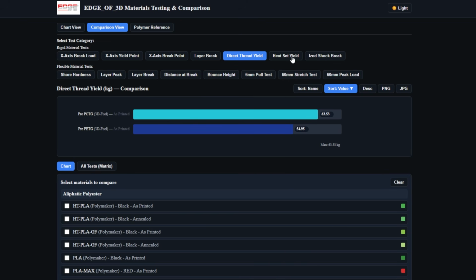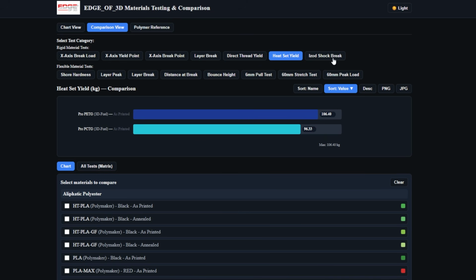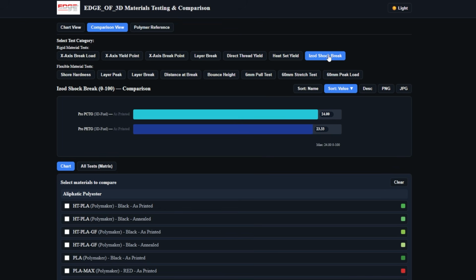And then when we get to heat set, they flip flop. PETG hangs onto a heat set a little bit better than PCTG does. I don't know the science behind it. These are just the results. And finally, the Izod shock test, that's the hammer hit. 24 versus 23.33. The PCTG was a little bit stronger material.